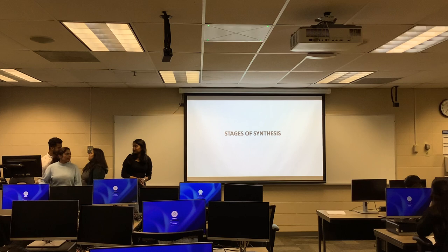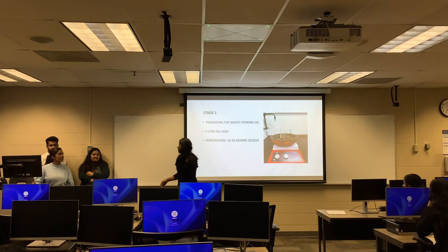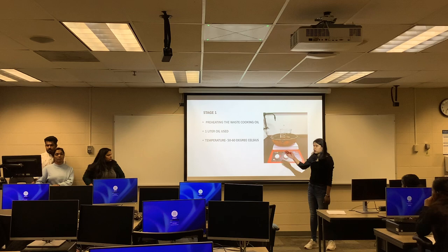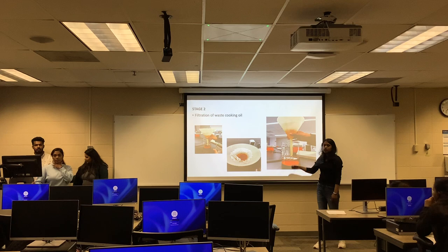Good afternoon, everyone. Now I'll be talking about the different stages of the synthesis. The first stage is preheating of the cooking oil. In order to reduce the water content in the cooking oil that we used, we preheated it for about 1 hour at 50 to 60 degrees Celsius. The next stage is filtration. To remove the solid particles in it, we filtered it.